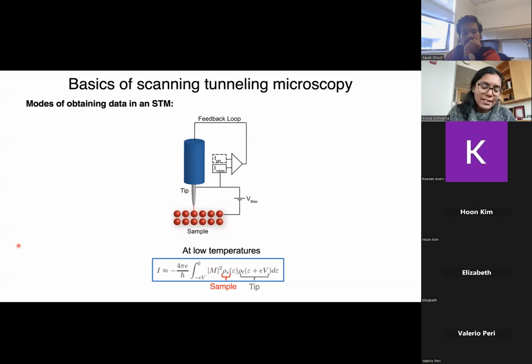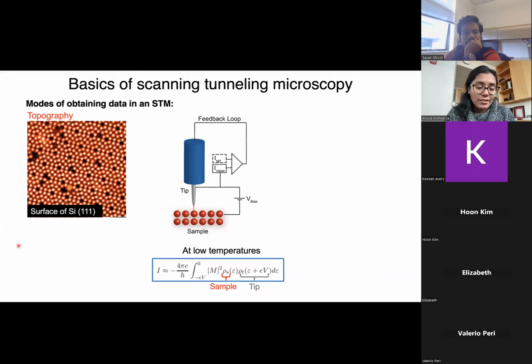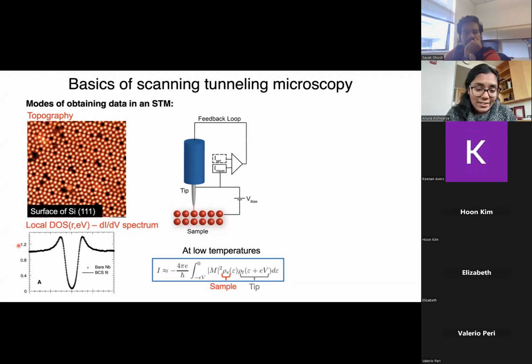We have this metallic tip that we bring in close contact with the sample at a specific bias. There's quantum tunneling of electrons that allows us to measure topography with very nice atomic resolution. We can also measure density of states by taking a derivative of the tunneling current with respect to bias. This is, for example, a spectrum measured on bare niobium.